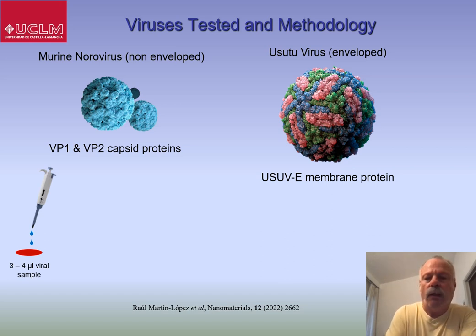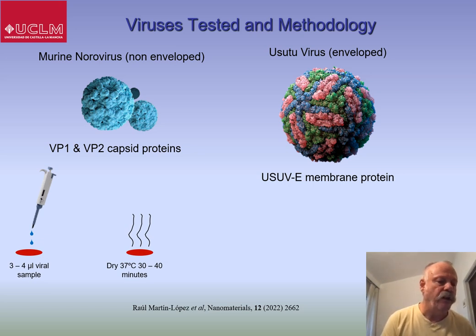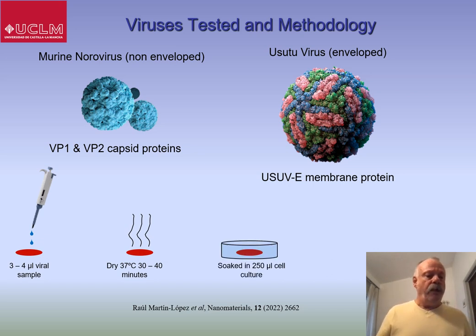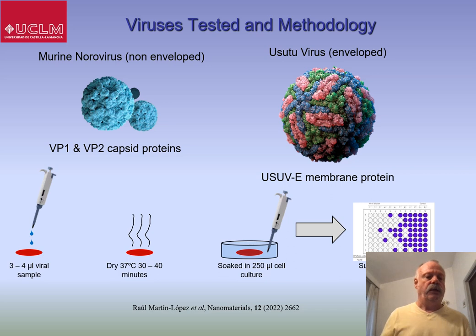Okay, so the basic method was the cloth that had been coated was cut into 5 millimeter discs, and onto this was dripped 3 to 4 microliters of the viral sample. Now the cloth and the virus were dried for 30 to 40 minutes at 37 degrees, to make sure there was a good interaction between the silver nanoparticles and the virus particles. Then the cloth was soaked in 250 microliters of cell culture to interact with the cells. And the supernatant of this was recovered, and the active virus particles rescued, and the level of activity, or the level of infectivity of these, was measured using a TCID 50 assay.